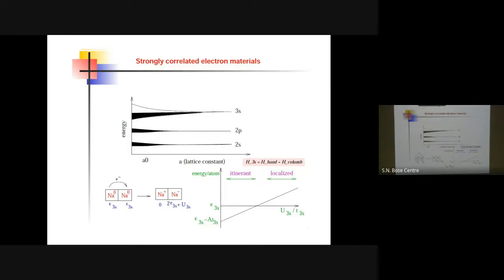I gain some kinetic energy by moving the electron from one site to another, but I also lose energy by creating double occupancy, by putting two electrons at the same site. The energy for putting two electrons at the same site is U. That's an atomic property that also depends on screening in a real compound, but that's a specific property. What can change is the hopping. When my lattice constant was small, my hopping was large, and therefore the kinetic energy gained overcame the energy loss by creating double occupancy. In this case, the kinetic energy gain is really small because I have put the atoms apart from each other. So you can already see the effect of this term U, depending on which regime you are in.